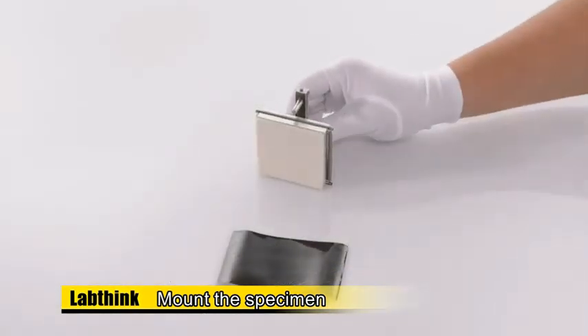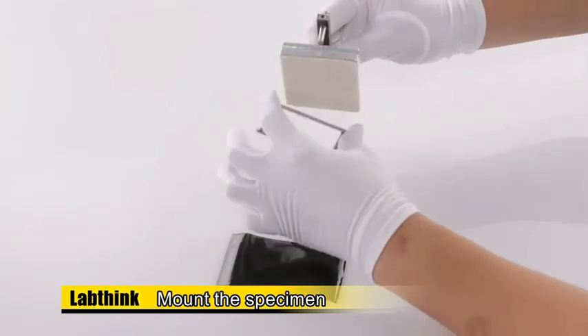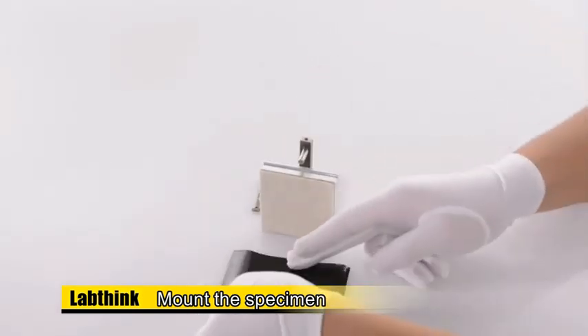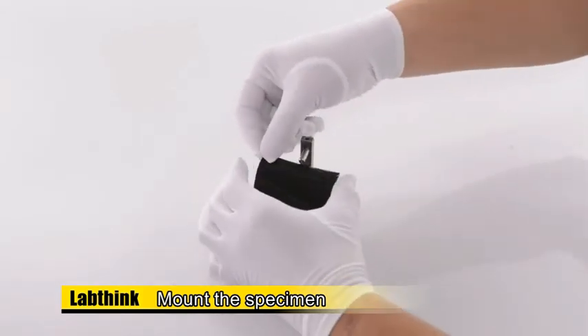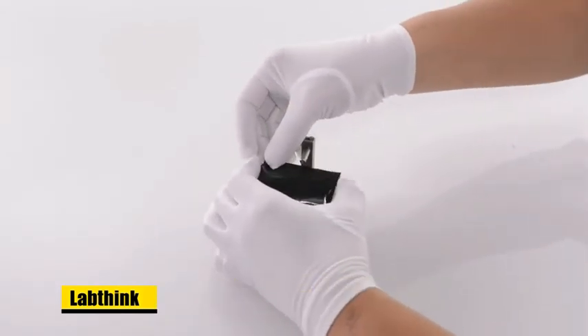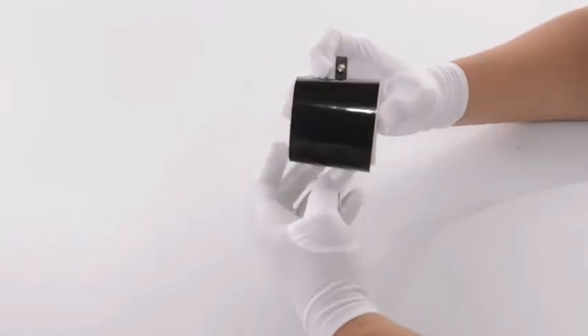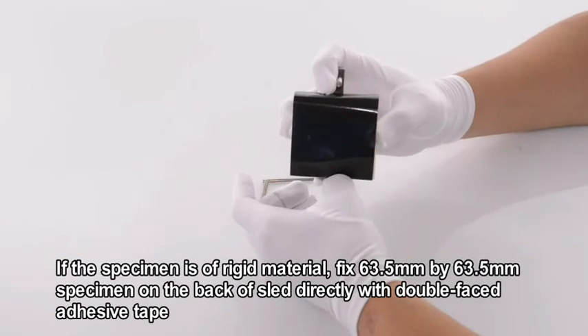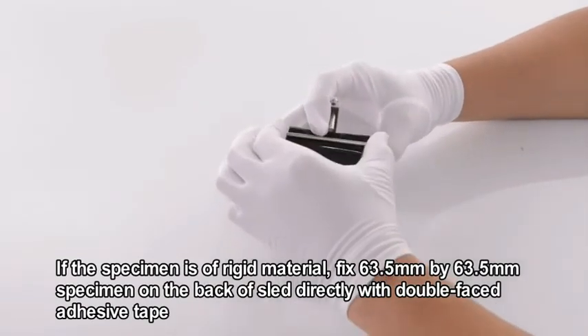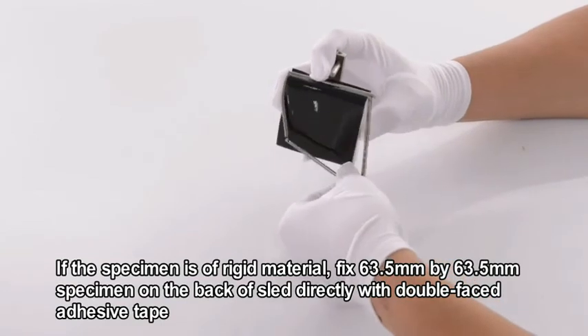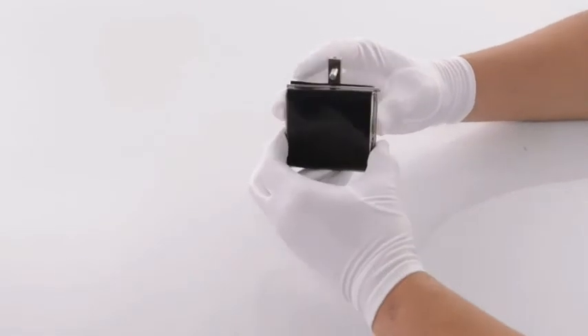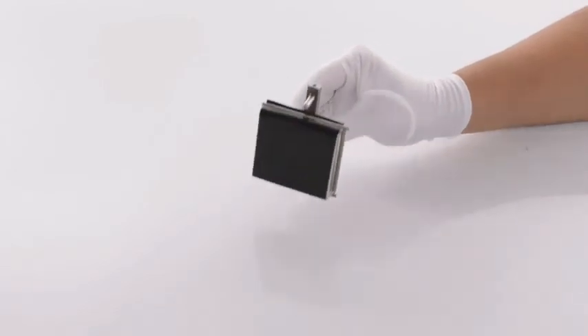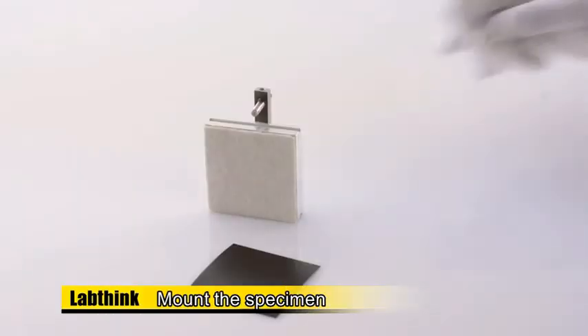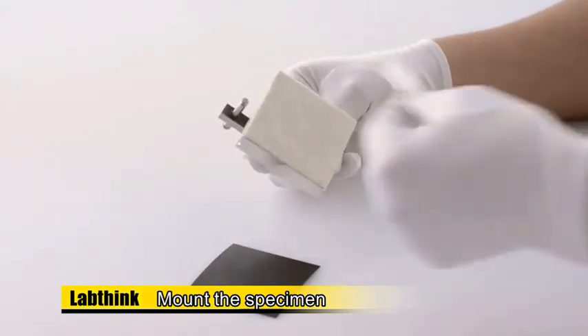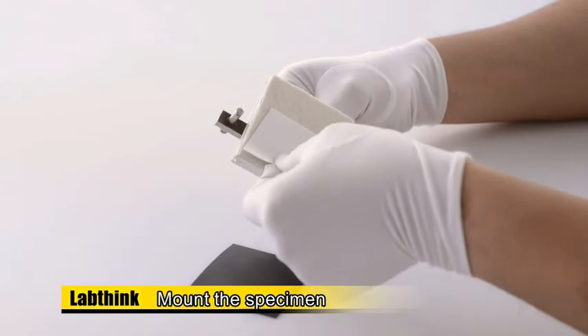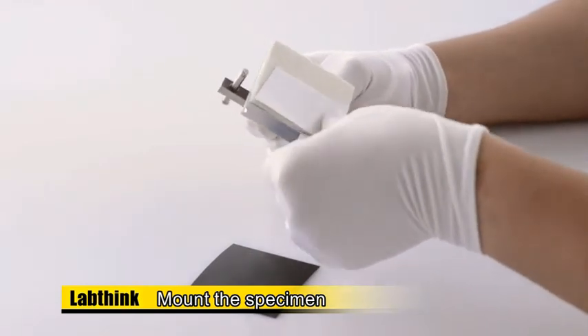Take the 63.5mm by 100mm specimen. Put the edges of the 100mm film specimen to the back of the sled using the specimen clamp and pull the specimen tight to eliminate the wrinkles. If the specimen is a rigid material, fix the 63.5mm by 63.5mm specimen on the back of the sled directly with a double-sided adhesive tape.